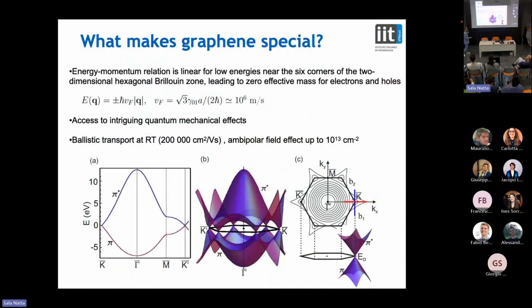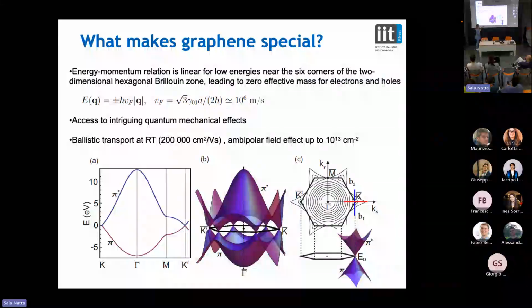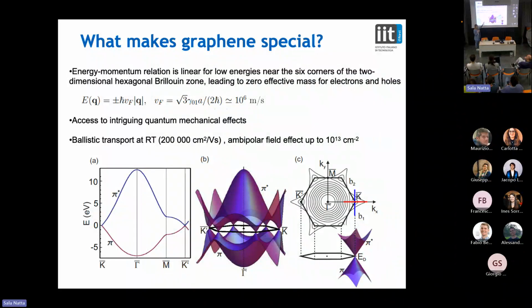Indeed, the first one is the electronic dispersion. If you ever happen to study the electronic properties of a material, you always end up looking in a book and seeing some lines that show, you know, oh, silicon is a semiconductor, so we have a valence band, a conduction band, and we have a gap, direct or indirect, and everything else. Graphene actually has a very peculiar dispersion of the electronic bands, and you have a linear relation. And that's what makes graphene special. It's this kind of energy-momentum relation that, if we plot the electronic bands, is linear for low energy.